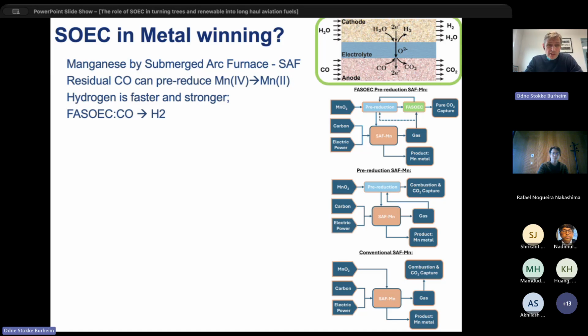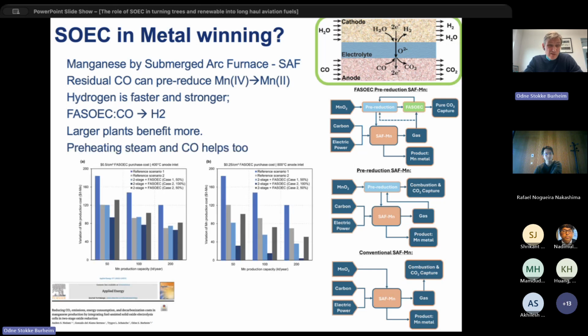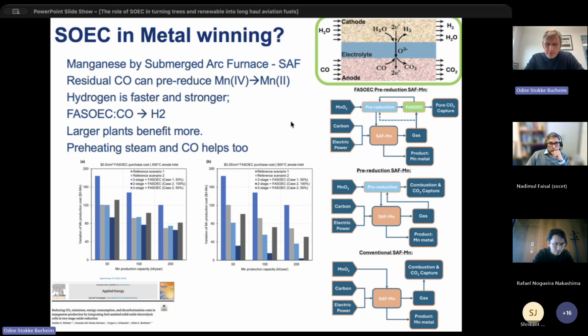Producing hydrogen from carbon monoxide, and these gases are also available at very high temperatures, so that's also good for this process. We found that larger plants benefit more from this, and preheating of steam is a bit important. And so if we look at the different cost of anodes, of electrolysis cells, so we assess sort of a price per square centimeter. It also matters a lot for how this sort of improves the economy of such systems. That we published a year ago,